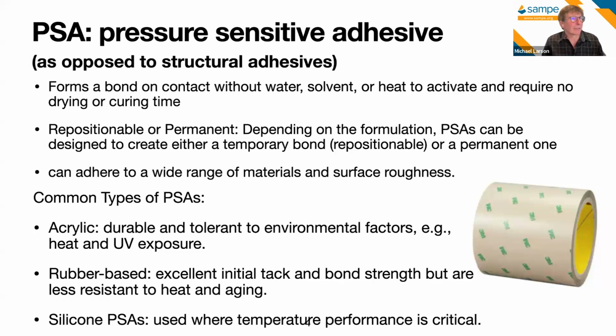So pressure sensitive adhesives, in general, we contrast these with structural adhesives. And like every adhesive, we can have failures that happen at the interface between the adhesive and the surfaces that they are bonding, or we can have failures inside. However, the nature of a failure inside the adhesive tends to be much different for this class of adhesives. And the nature of that bonding to the surface is different. Most notably, it tends to be much weaker. And so it is something of an irony that we get a strong adhesive bond out of something that often seems to have very low work associated with debonding the surface contact.